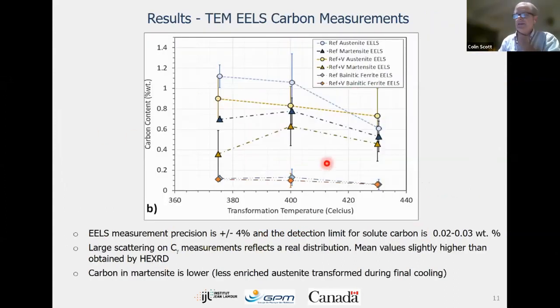We did a similar experiment ex situ using electron energy loss spectroscopy in the TEM. So I won't go through this because I don't have time to go through all the data. I don't have time to explain it all. But what you can see is the round points here. This is the retained austenite. The triangular points here are from martensite, and the diamonds here are from bainitic ferrite. So you can see the evolution of the carbon content and the difference between the three phases.